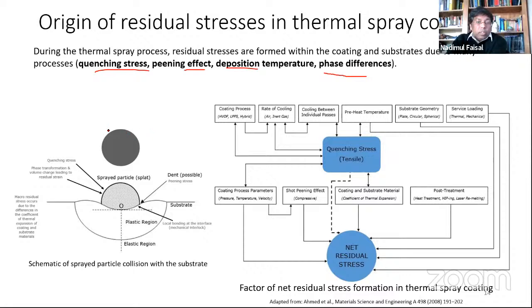So assume you have a single particle landing on the substrate. Because of high velocity, you're likely to see a little deformation, plastic deformation or elastic deformation, both could happen. The particle will become flat, and then the particle will have a quenching stress. At the same time, the phase transformation could happen. That can lead to a volume change. As soon as the volume change happens, the strain will build up.